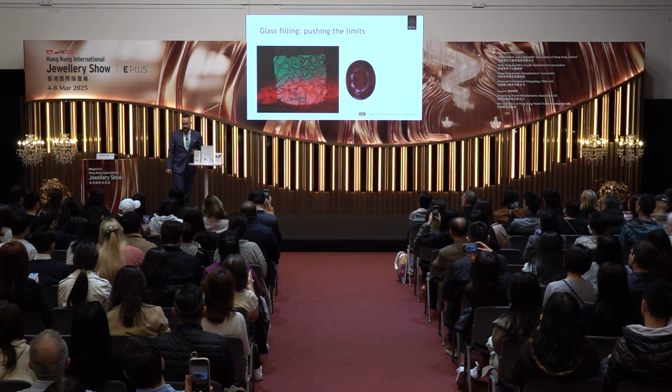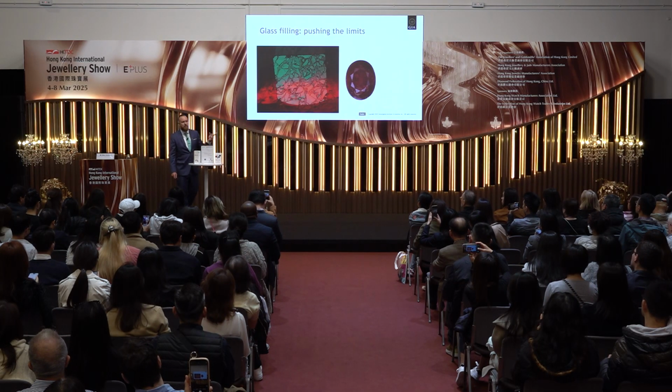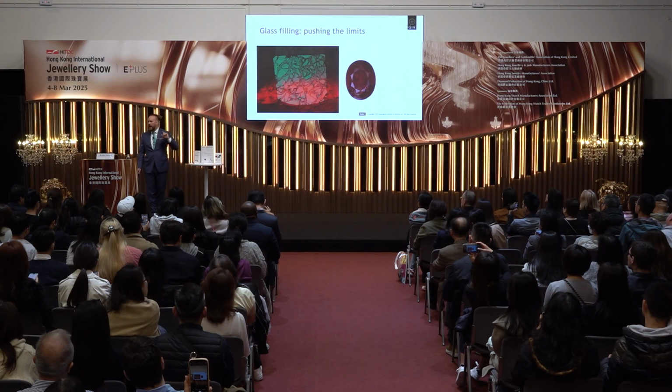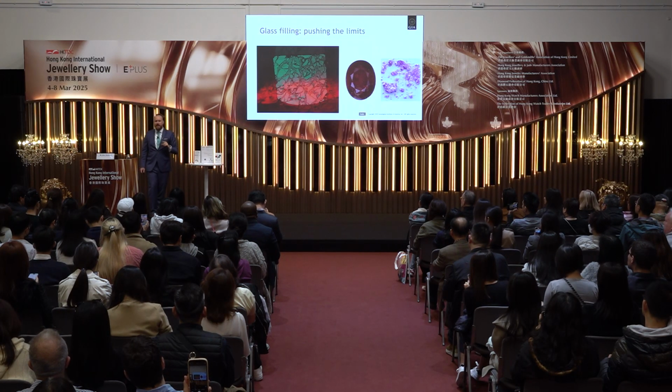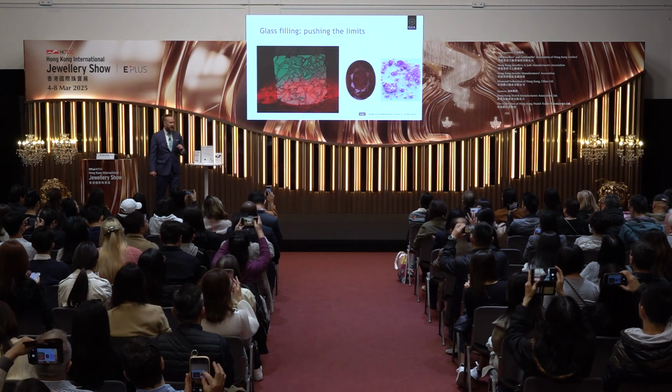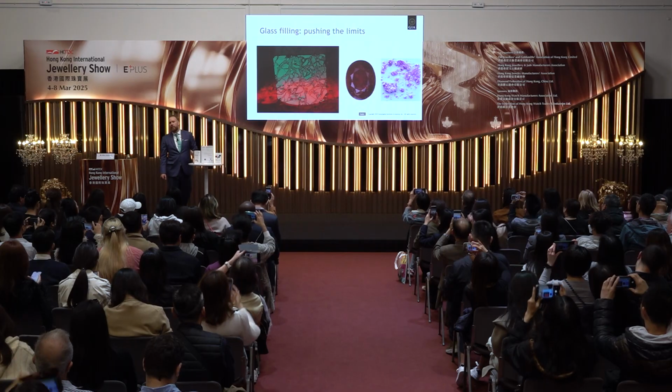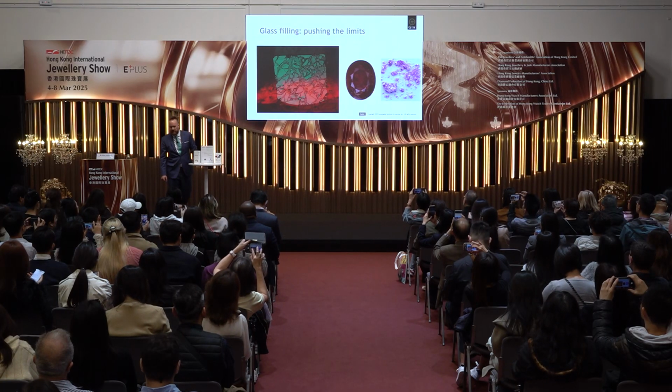Can I destructively test this? So he put this in the jeweler's pickle, a standard solution used in any jeweler's workshop. And this is what came out after a couple of hours. So this is why it is so important to be able to recognize lead glass filled material.